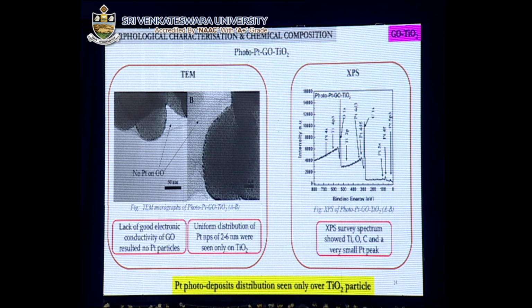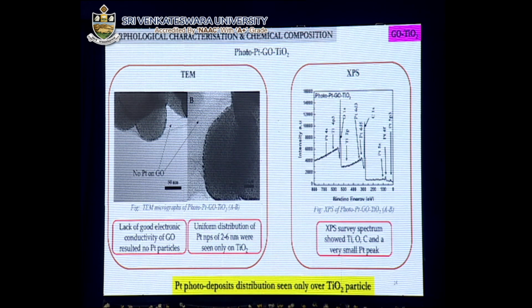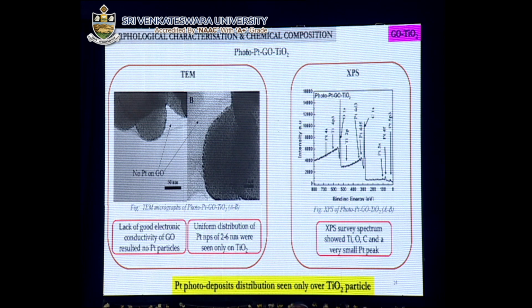has lesser conductivity compared to graphite. So the conductivity issue played a major role, and we couldn't find any platinum on the surrounding substrates. So when we use graphene oxide as the substrate for the electrocatalyst, it's not possible to use the photocatalytic method, and this is a major hindrance for cost effectiveness. But of course, thinking from the angle of graphite, we can say that this method still holds some opportunity. And the XPS also confirmed that the platinum was very minimal in quantity and did not show intense peaks.